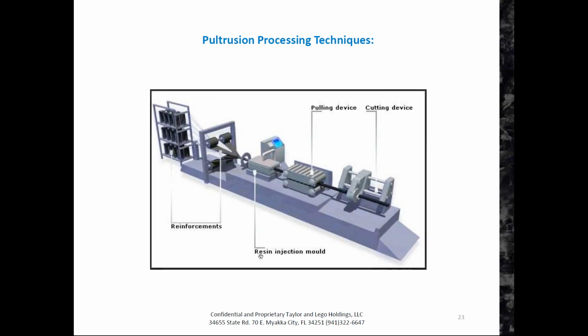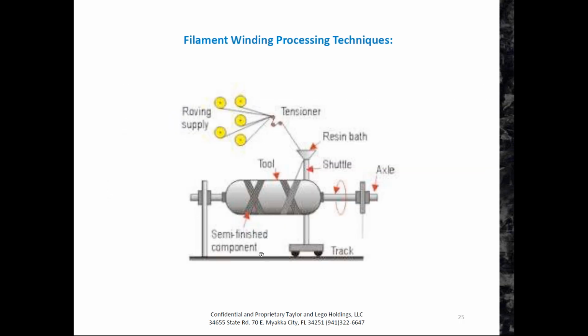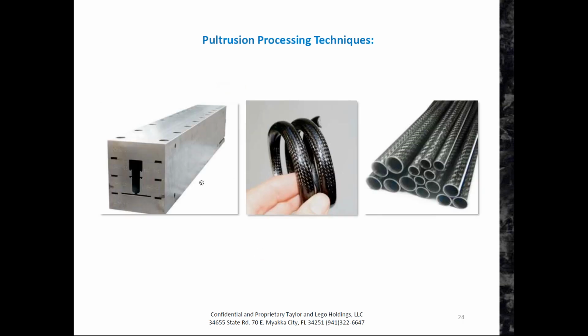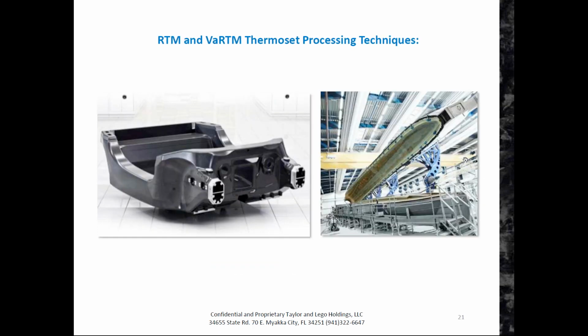Again, I won't spend too much time on it. So this is a typical die system, and they even make die systems like this where it actually impregnates as it goes through that process, so there's not a separate resin bath. They can do spirals and spring-type designs like this, helix shapes, and then here's also pultruded tubes, which are pretty typical.